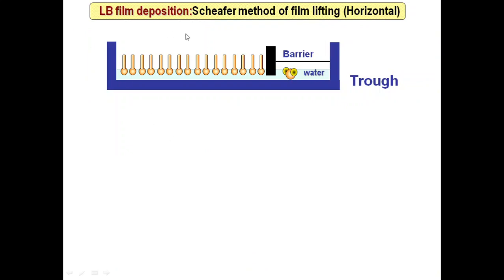And there is another method which is called the Langmuir-Schaefer method, and using this method, somewhat rigid Langmuir monolayers can be transferred. And here the substrate is used horizontally, dipped horizontally, not vertically, and it touches the monolayer and then is lifted up, such that the film is transferred onto the solid substrate. This is called the Langmuir-Schaefer deposition technique, and it is used for somewhat rigid Langmuir monolayers.